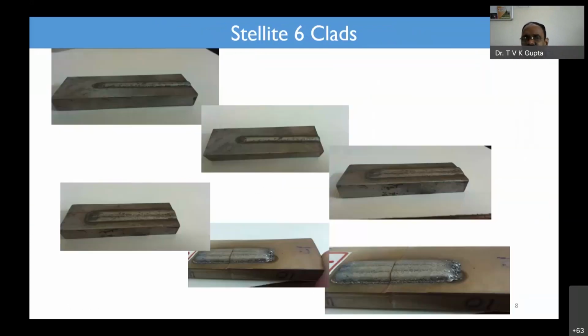So this is the first set of experiments which we tried with our industry partner. Initially, when we went to the industry, they were not interested in changing the parameters, but they wanted some sort of research, because on the components they had made, they might have seen something but ignored it. In the substrate, when you are depositing, there is a small amount of distortion which we observe. Though we considered it a perfect plate, because of the thermal deformation, we saw distortion on the substrate. So the first thing we targeted was how we can reduce the distortion.